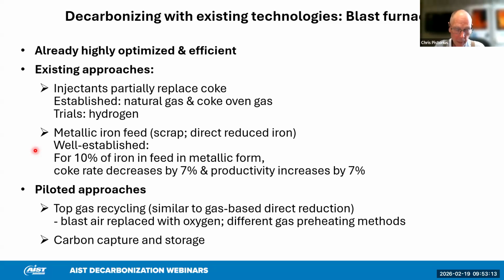And then there are some piloted approaches. There historically have been some large-scale pilots in Europe under the ULCOS program to look at top gas recycling, and there is a current instance of that technology which is about to be trialed in India, essentially the blue blast furnace, where similar to what is done with gas-based direct reduction, the top gas is recycled to give each carbon and hydrogen atom the maximum possibility to grab oxygen from the iron ore.